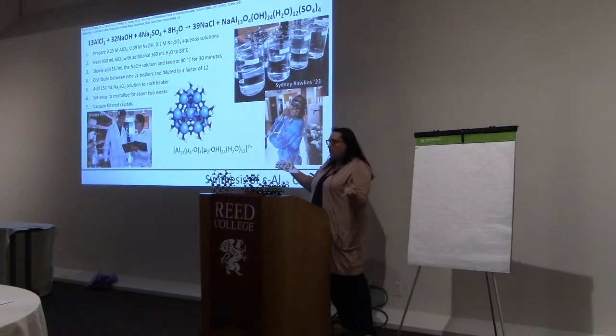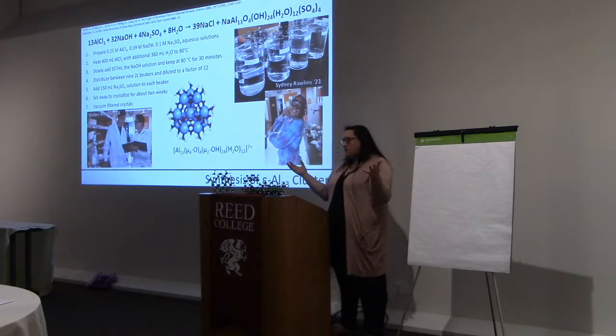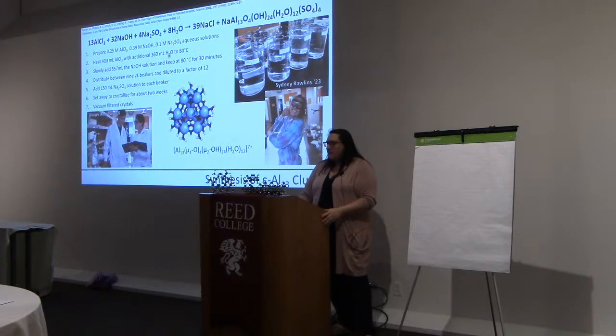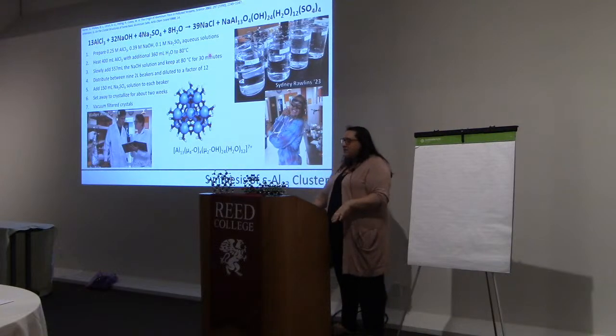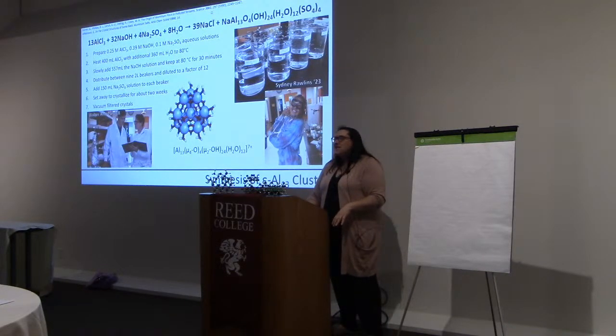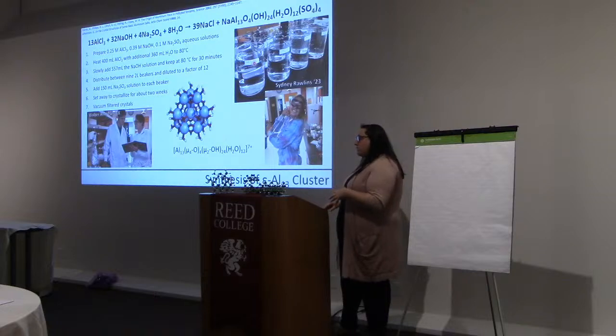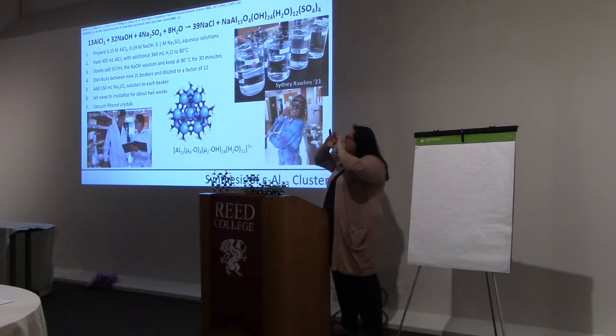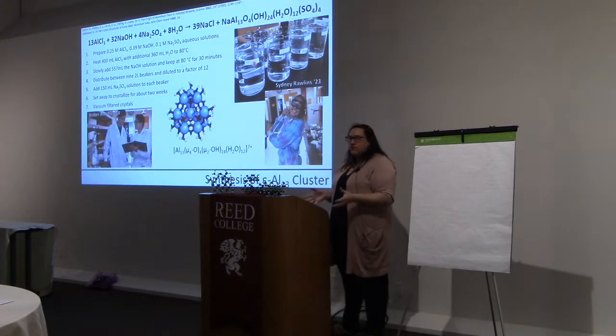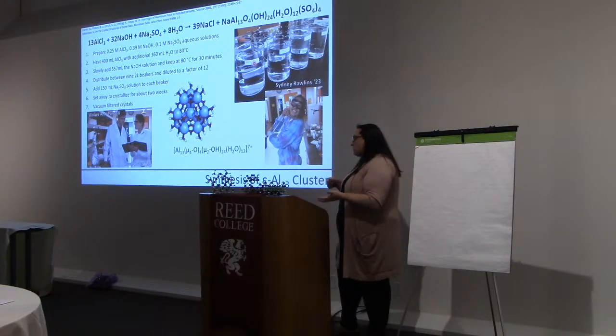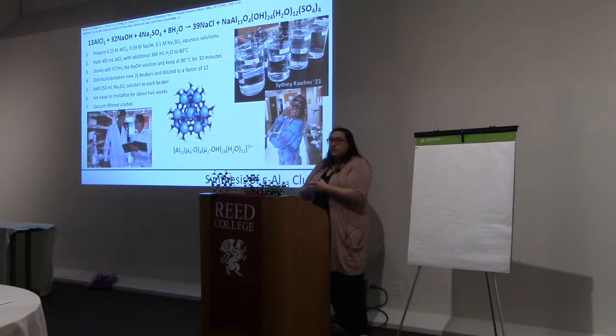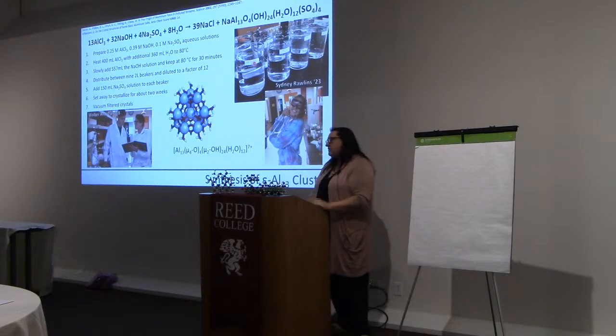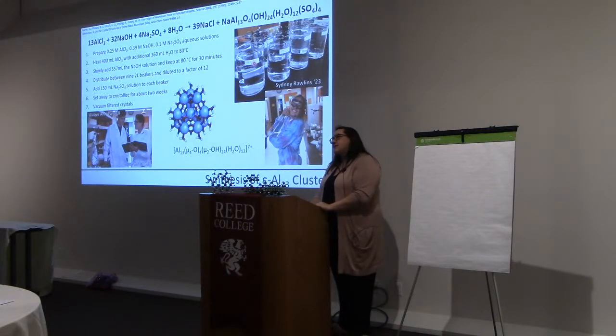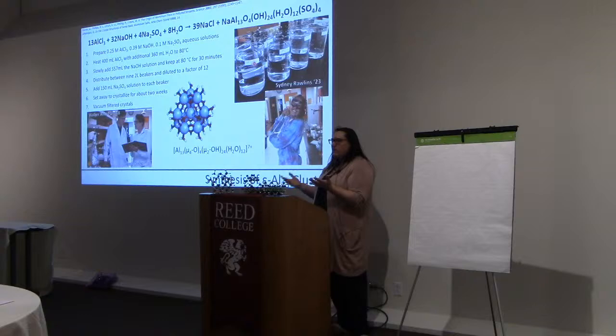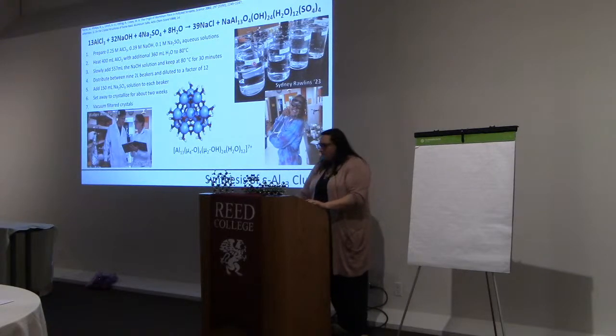a factor of 12 in all these beakers, so it's super dilute. And it's soluble when it has chloride counterions. But after they dilute it, they add sodium sulfate, and it is insoluble with sulfate. So after about 2 weeks from this very dilute solution, the sides of these beakers are just covered with crystals. We can decant and then scrape those crystals off, and we have this nice cluster that we can start with. And so my students have done this over the last six years, maybe 7 or 8 times at SOU. We've become pretty good at this.